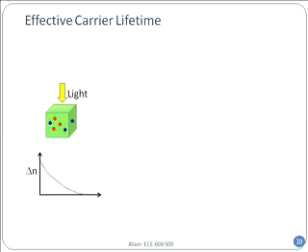And in experiment, if you look at the output light that is coming out, you will see it is decaying as a function of time. So the x-axis is time, the y-axis is delta n. And t equals 0 in this one is when I have turned the light off. I just turn the light off and look at how the photons are coming out. So from experiment, what I will get is something called a tau effective. That's how I'll see the whole thing decaying.